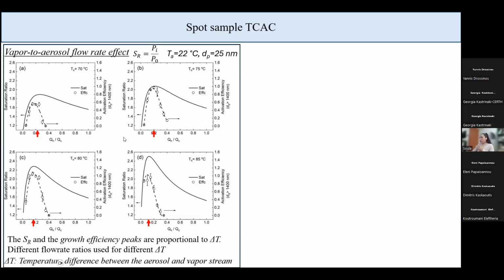Now, another thing that we notice here is that as the temperature of the water increases, the optimum hot water vapor to aerosol flow rate decreases. For example, in the first case, the optimum ratio is at approximately 0.25, while in the last case, the optimum ratio is at approximately 0.15. So in the following experiments for the further characterization of the setup, I used a different flow rate ratio for the optimum operation.